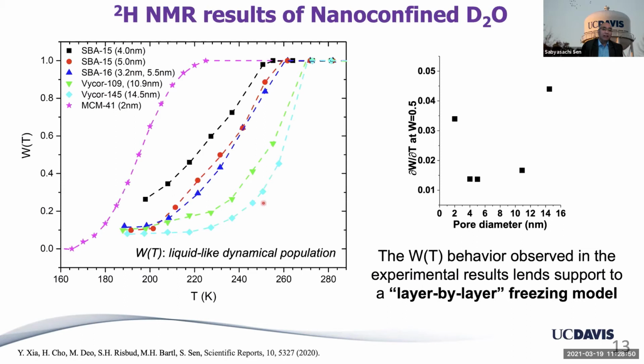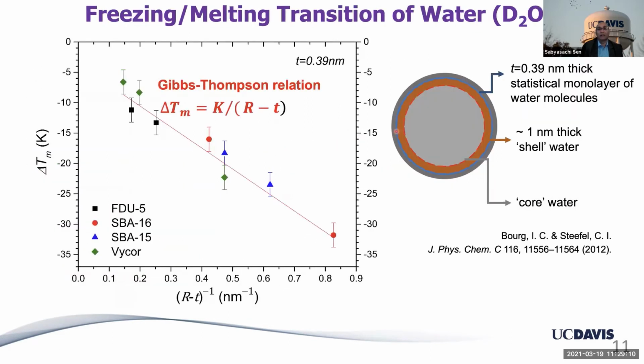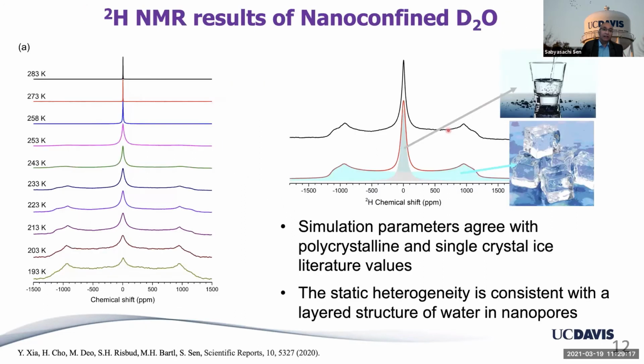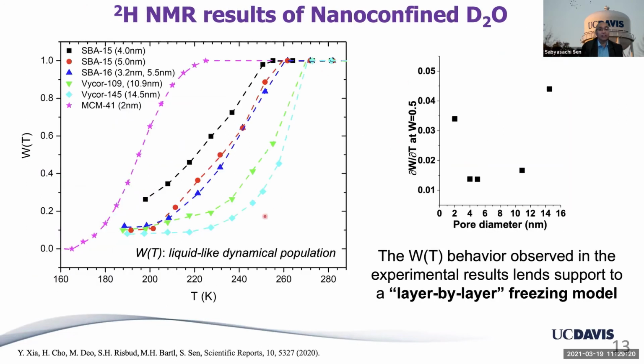On the other hand, for the very large pore size, most of it is like the core structure, and very little of the stuff is in the shell around it, because it's a pretty large pore of, say, 15 nanometer or so. So the shell-like water that I showed before, this brown layer, the shell-like water fraction is pretty small. Mostly it is a core-like structure, and therefore they also freeze over a narrow range. But in between, you can have a progression. So the water near the shell, or near the interface, behaves differently compared to near the center. So this is like a layer-by-layer freezing of water inside these pores.